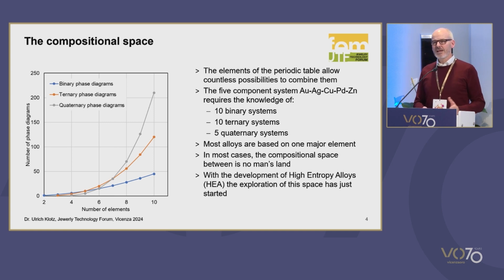If you want to select alloy developments for an alloy, you have to combine them. And you have to map the properties as a function of composition and temperature. And this is usually plotted in a so-called phase diagram. Now, if you have two elements, you can make one binary phase diagram, just one mixture, gold and silver. If you have three elements, gold, silver, and copper, you have one ternary system, but you have gold and silver, you have gold and copper, and you have silver and copper, so you have three binary systems.